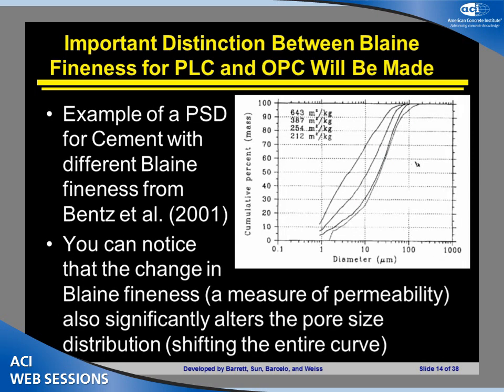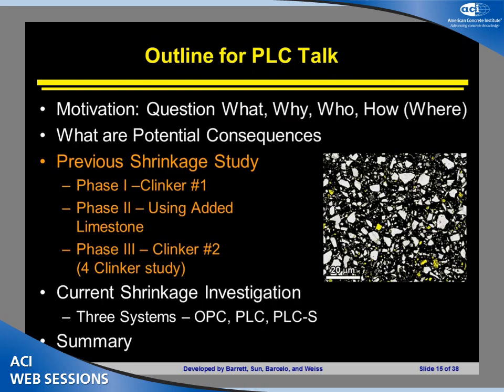Right, now I want to point this out really quickly here, and I'm going to ask you to remember this particle size distribution curve. Here you can see a particle size distribution curve, and this is for conventional Portland cements. And this was out of one of the studies I mentioned that said finer cements are more prone to crack. But what I want to point out is as the fineness has been changed, you see these curves shift pretty substantially over toward the left-hand side of the screen, and the whole curve slides relatively uniformly. I'm going to try to contrast this with what we see in the PLC systems to show you that we really are going to get a different particle size distribution, and as a result of that, we're going to get a different pore size distribution inside of the material.